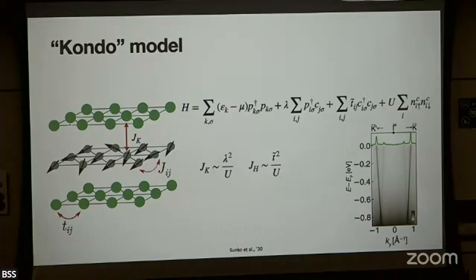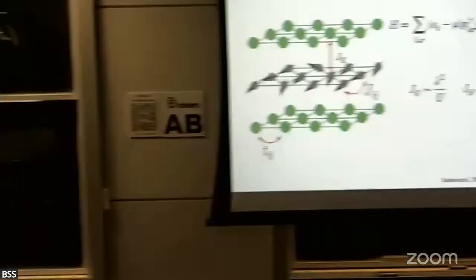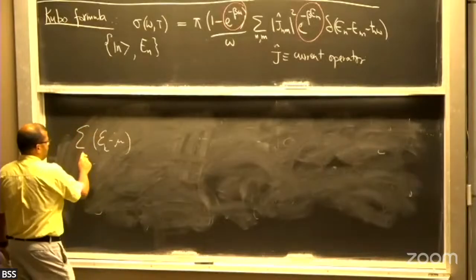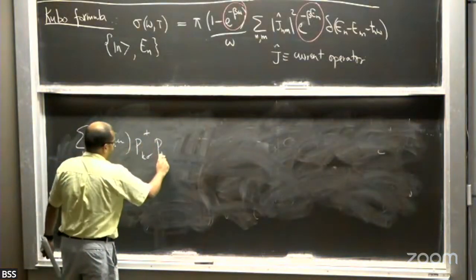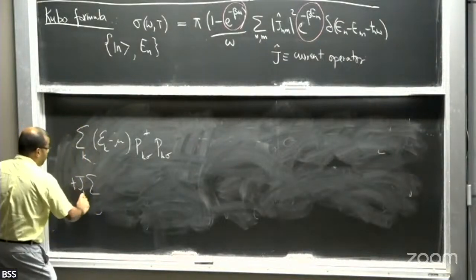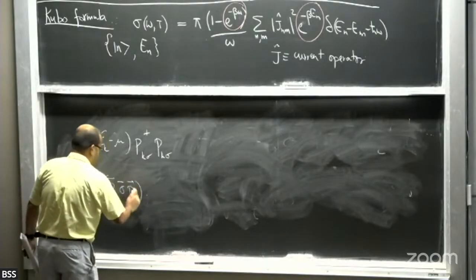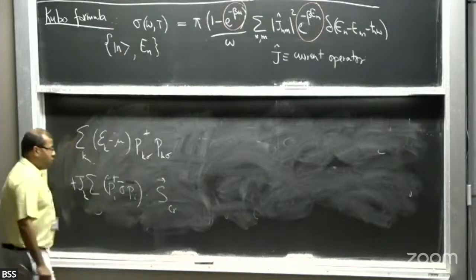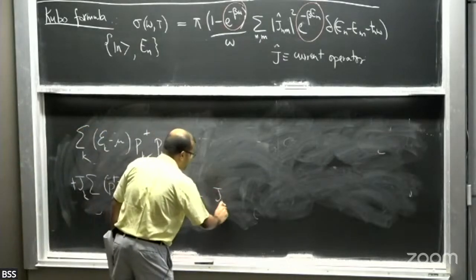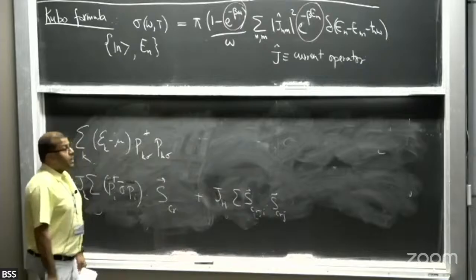Just for the sake of concreteness, I will write it out. So you have your epsilon k minus mu for the palladium, and Kondo coupled to the chromium spins. And then there is some super exchange between the chromium spins as well. Okay, and all these coupling constants are actually known from some fits to the spectral functions that I could come back to if anyone's interested.